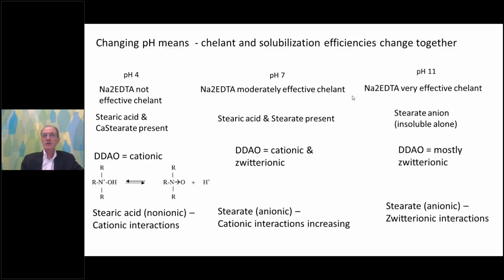Remember, it can change its total micellar composition, right, as a function of pH. And then at very high pH, now our EDTA is doing its job completely. We have primarily stearate anion present. Stearate's not going to be soluble on its own, though, at room temperature. But now we have our zwitterionic amine oxide present in order to form mixed micelles.